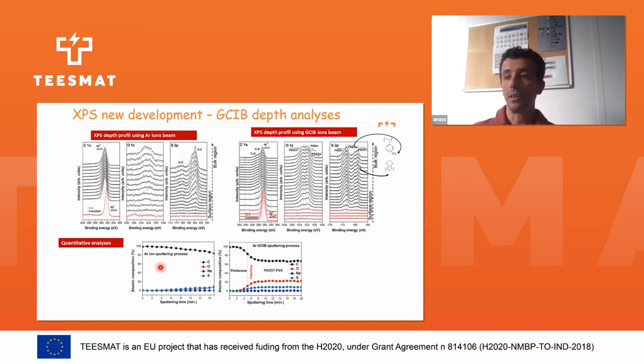And also, if we do quantitative depth profiling analysis based on GCIB, we can see the pentacene group and the PEDOT:PSS. So we have a very nice depth profile, and we can follow the concentration of carbon, oxygen, sodium, and sulfur in our materials. But in the case of ion-based depth profiling, it is completely useless because we lose lots of information, especially at the interface. The information at the interface was lost.